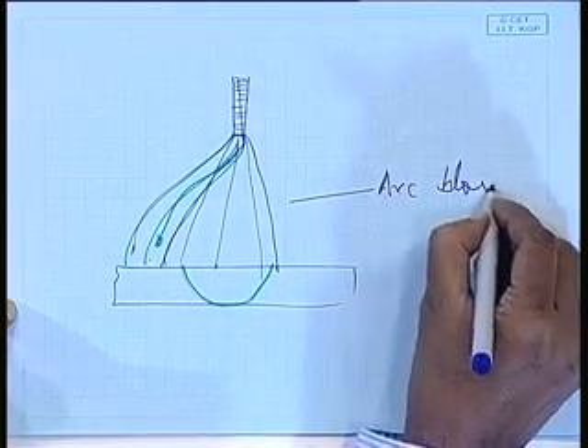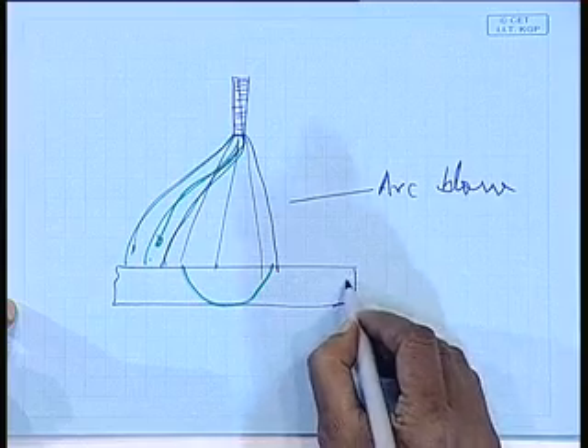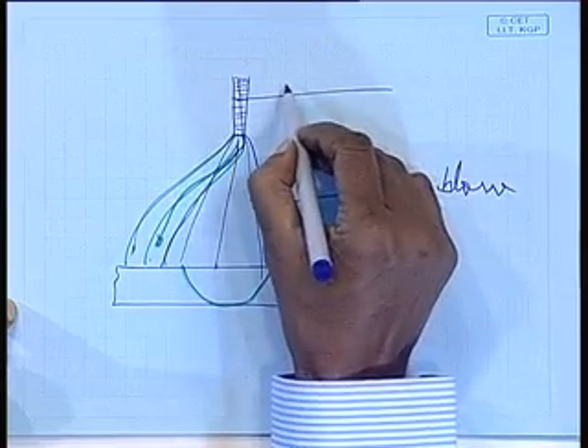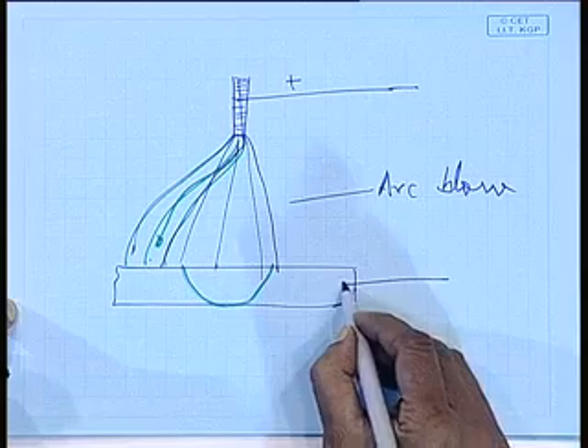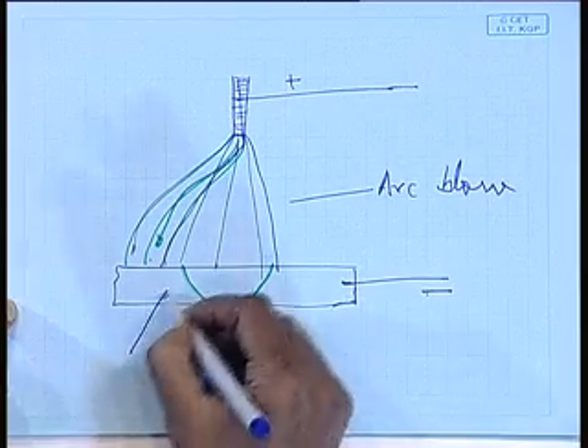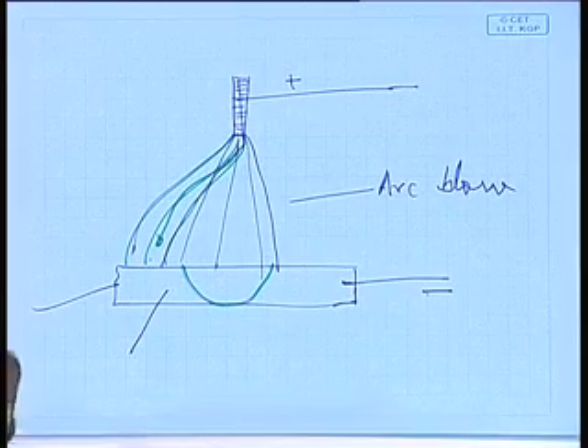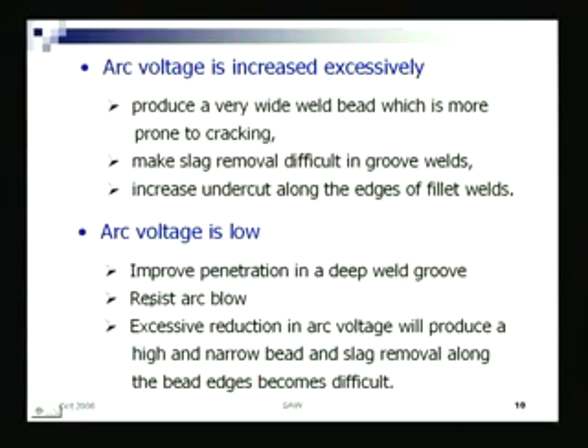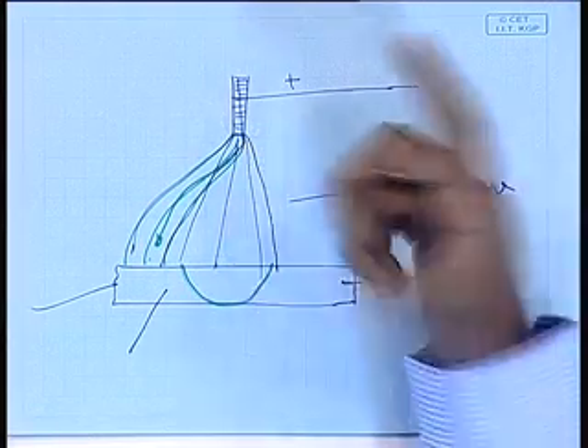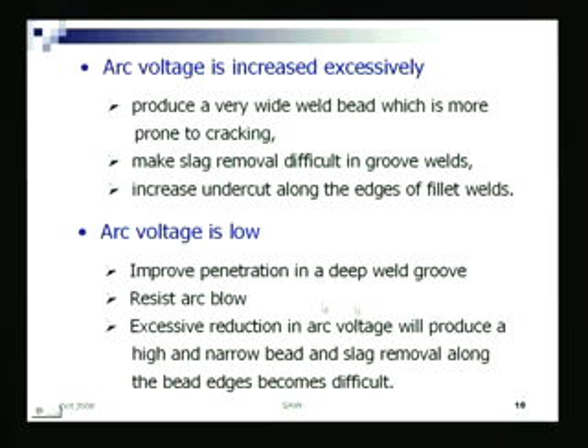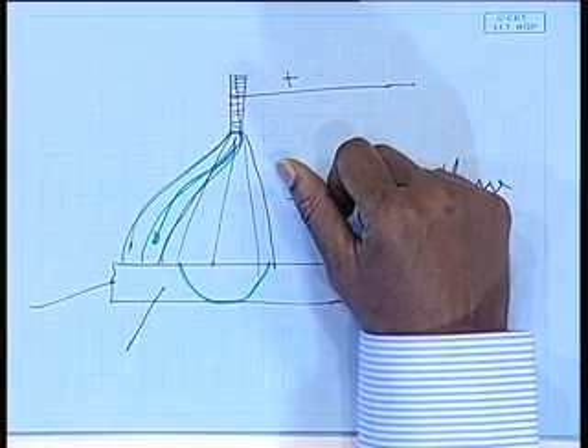Then what you will have to do is recheck where the other terminal is. Suppose you have the electrode positive here, here is the negative terminal connected. So, you have to connect at several places, such that undesirable magnetic field is not formed. Anyway, if the arc length is smaller, then chances of arc blow reduce. Now, excessive reduction in arc voltage will produce a high and narrow bead, and slag removal may become difficult.